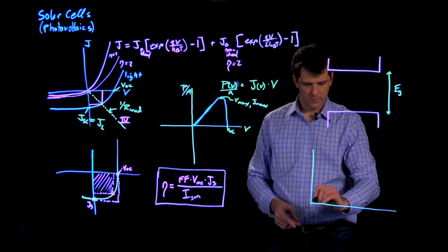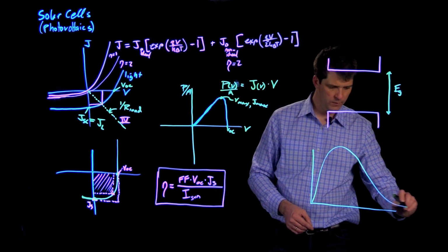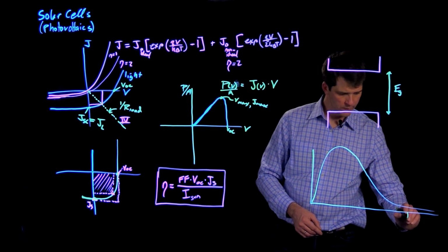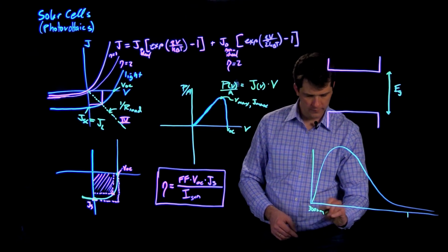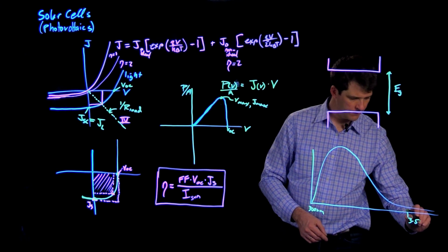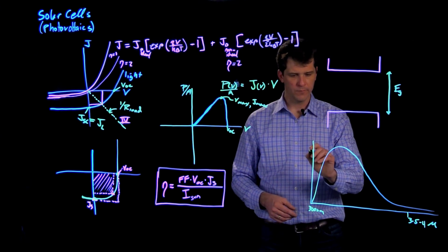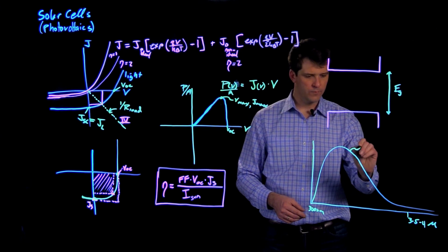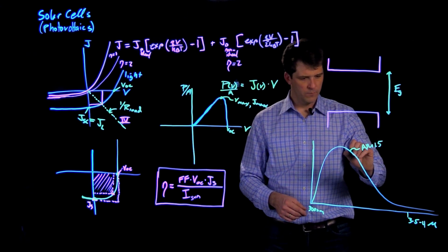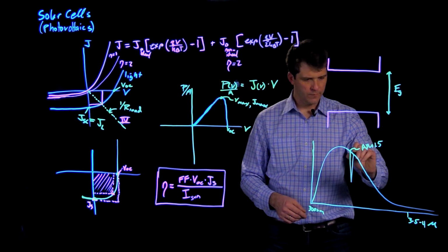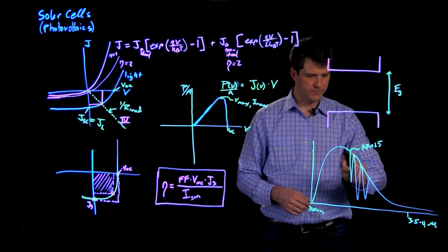If we have a semiconductor with band gap Eg, it can absorb a portion of the solar spectrum, which we can plot now as an imaginary black body spectrum. The real one has some more details due to atmospheric absorption, but basically if we go between about 200 or 300 nanometers out to something like 3.5 to 4 microns, we capture almost all the power coming to us from the sun. On Earth, we call this the air mass 1.5 spectrum, and that would refer to the real one that looks like the black body curve, but with some very sharp dips due to atmospheric absorption.